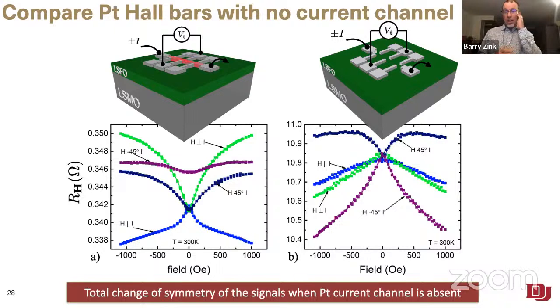This is a first look, and a very imperfect one honestly, to see if we can prove to ourselves that any of these changes have anything to do with spin and have anything to do with the antiferromagnet. We did it by creating the same sort of Hall bar, except we removed the current channel, so that now all the current flowing in the experiment gets down into the LSMO and then comes back out.